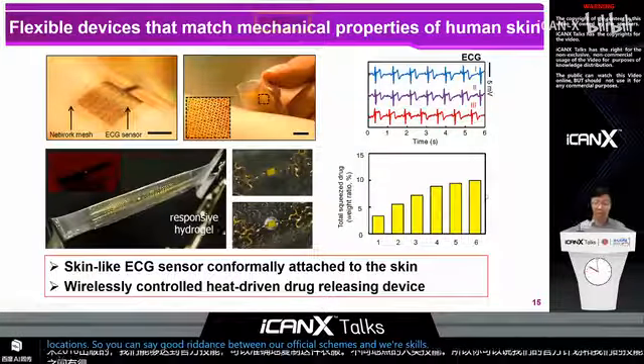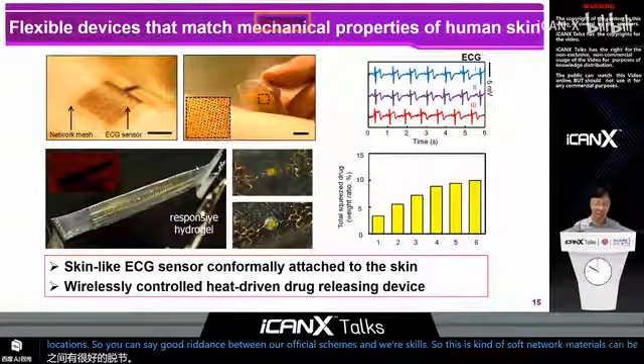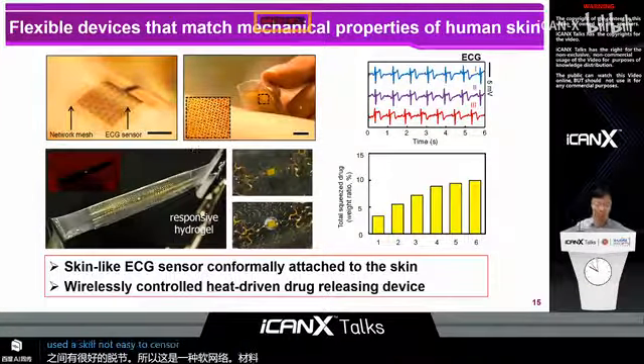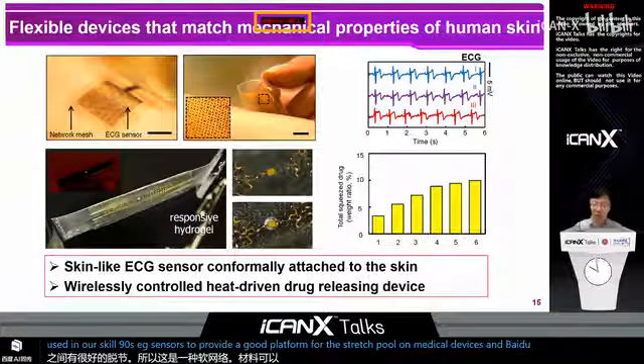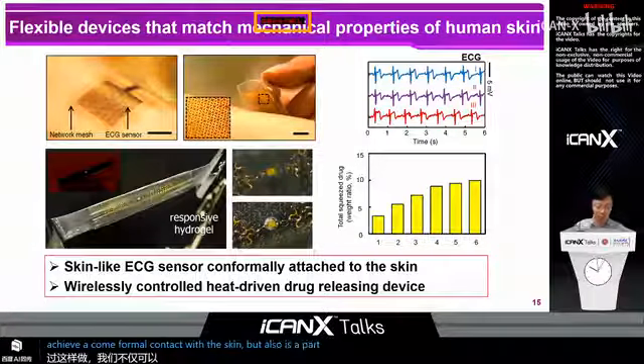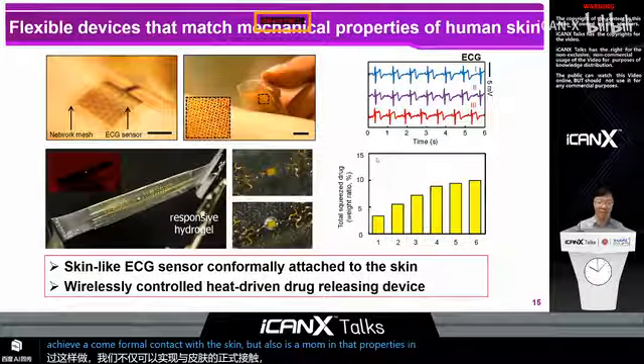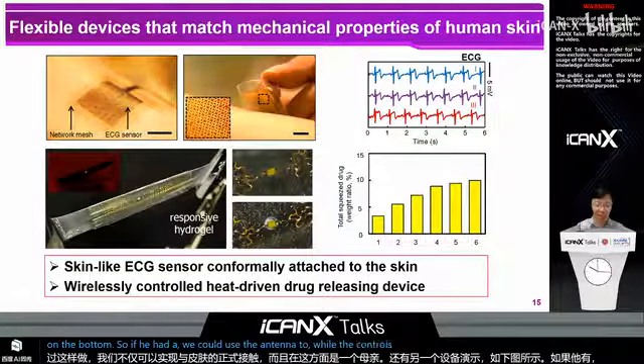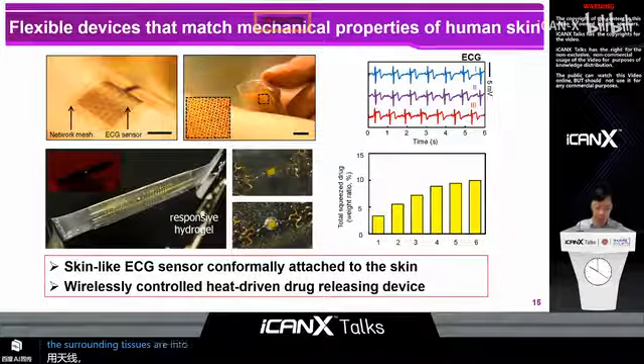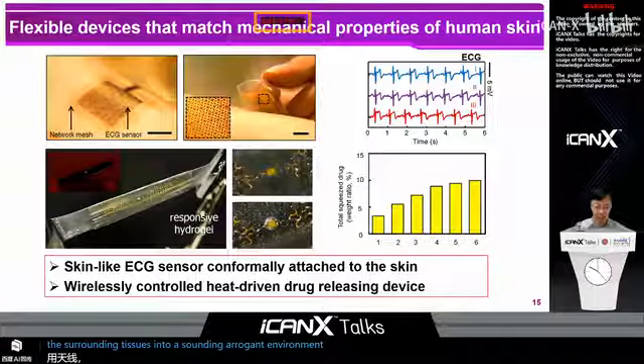So this kind of soft network material can be used in a skin-like ECG sensor to provide a good platform for stretchable biomedical devices. By doing so, we can achieve not only a conformal contact with the skin, but also biomimetic properties. Another device demonstration is shown on the bottom. Here we can use the antenna to wirelessly control the release of responsive hydrogel into the surrounding tissues, into the surrounding environment. The mechanism here is electromagnetic coupling.